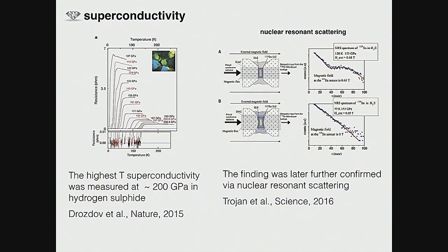Another experiment that the same group did later is a nuclear forward scattering experiment that is very clever, interesting. The way it's conducted, the sample is subjected to high pressure and low temperature. So you have to imagine 200 GPa in a cryostat and a magnetic field, and they change the temperature of these samples. They put a very small tin foil surrounded by the sample that becomes superconductive, and they show that the sample becomes shielded from the external magnetic field when it becomes superconductive.